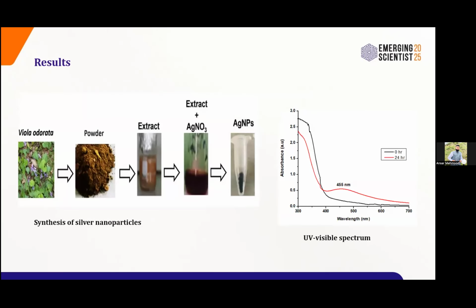First of all, the synthesis of nanoparticles. We used the Viola odorata whole plant extract that was converted into powder, and then we made an extract using distilled water. After that, the extract was mixed with silver nitrate, and you can see in an Eppendorf tube the pure silver nanoparticles. They were characterized using UV-visible spectroscopy, and we found a unique peak at 455 nanometer, that is the SPR of silver nanoparticles, and it showed the synthesis of silver nanoparticles in the reaction mixture.